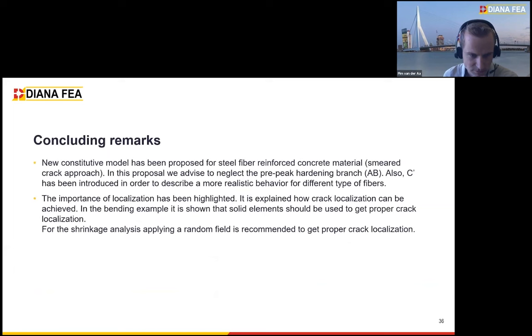That's this example. So then, quickly summarizing the things we just discussed. A new constitutive model has been proposed for steel fiber reinforced concrete for a smeared crack approach. In this proposal, we advise to neglect the pre-peak hardening branch, the AB. Also, C prime has been introduced to describe a more realistic behavior for different types of fibers, and also to improve crack localization. In the second part of the presentation, the importance of crack localization has been highlighted. This explains how we can get a better crack localization. In the first example, that was by using solid elements instead of shell elements. And in the second example, this was achieved by applying a random field over the tensile behavior.